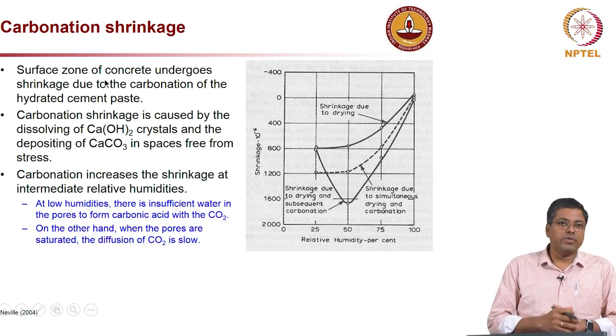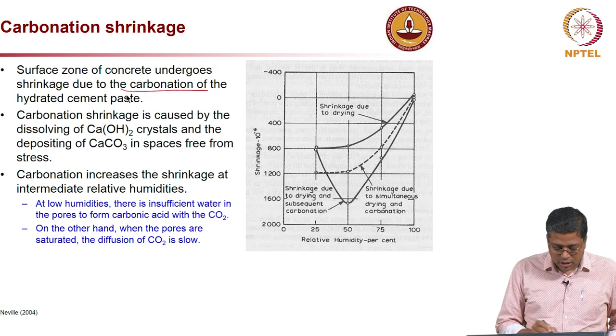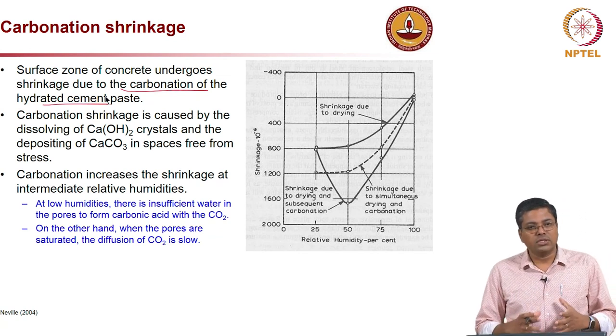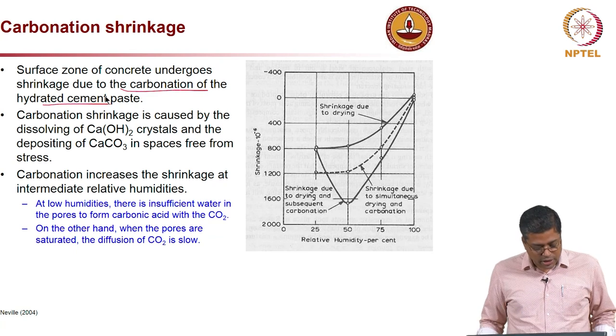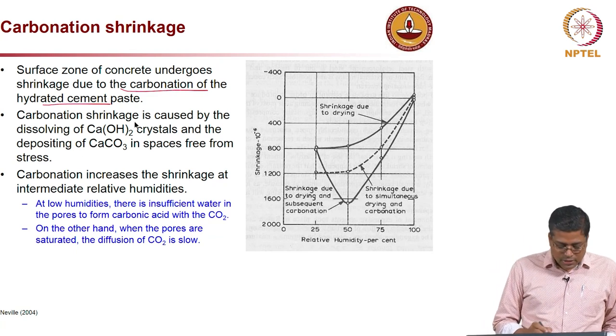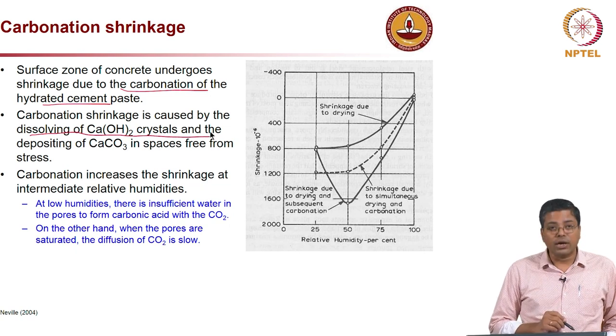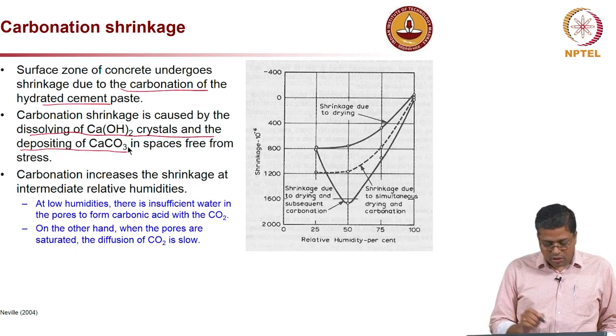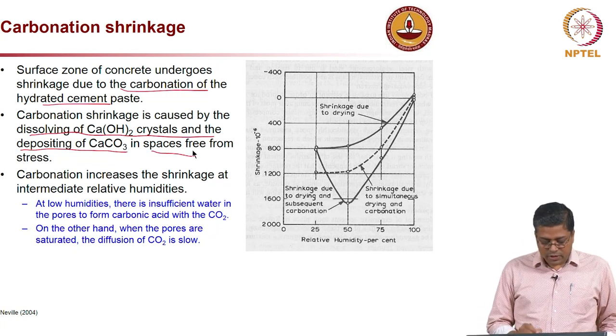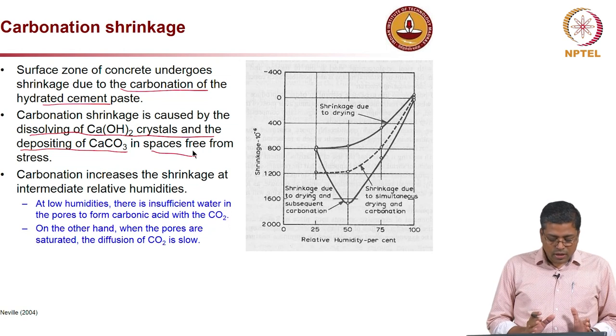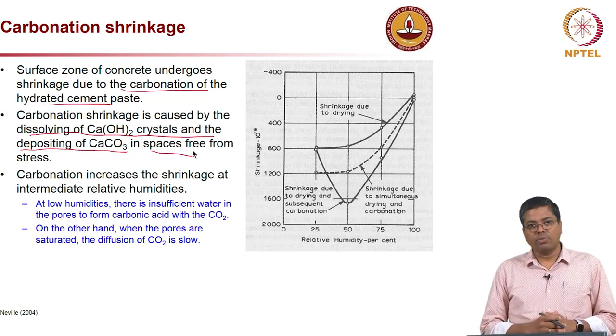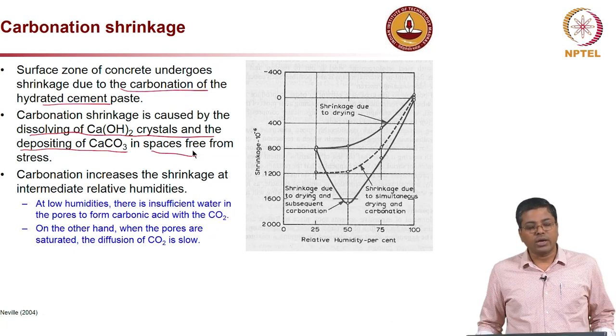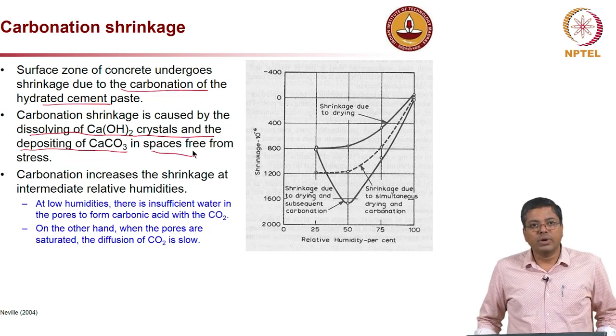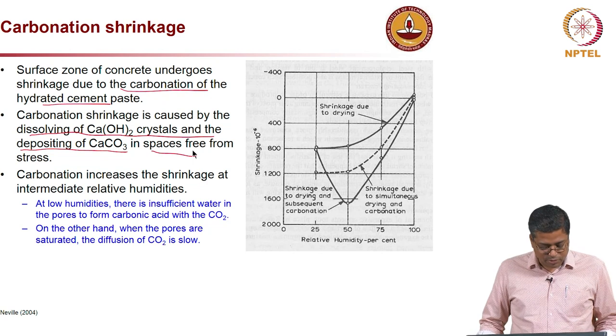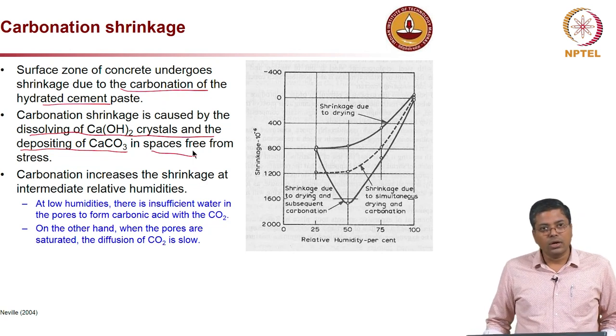Here the near surface concrete will undergo shrinkage due to the carbonation, because that is the region which gets carbonated first. And how is it happening? It is caused by the dissolving of calcium hydroxide crystals and the deposition of calcium carbonate crystals in the space which is free from stress. So, calcium carbonate is the product of this carbonation reaction between calcium hydroxide and carbon dioxide, and it occupies spaces available within the concrete which are free from stress, and eventually this leads to shrinkage.